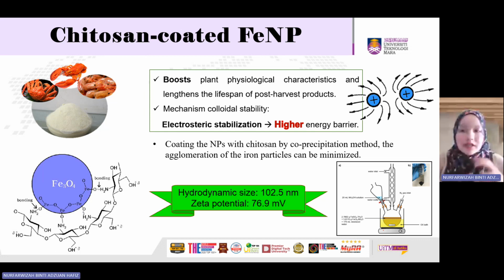Then, the electrostatic repulsion of chitosan further enhances the stabilization effect. The combination of both steric repulsion and electrostatic repulsion yields an electrosteric stabilization effect. With this stability, a higher energy barrier can be formed to prevent the agglomeration. As far as is known, by coating the nanoparticle with chitosan by the co-precipitation method, the agglomeration of iron particles can be minimized during the synthesis process.